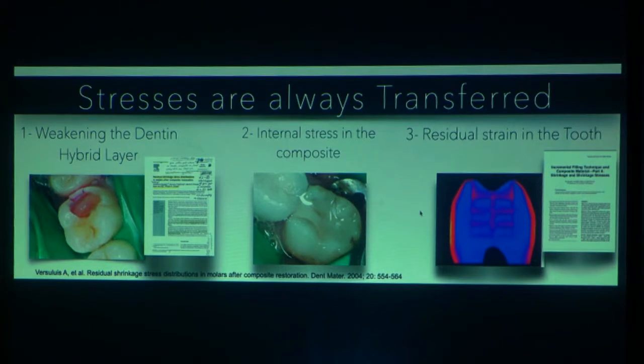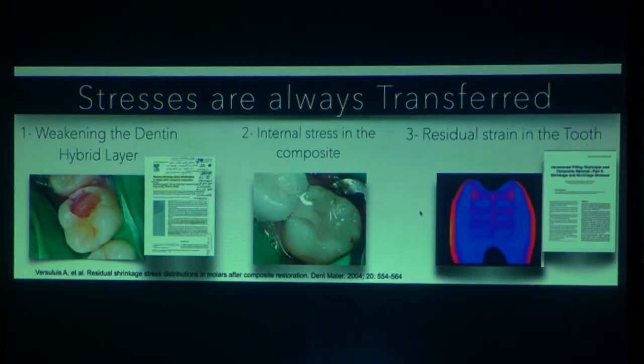3M spent over $1 million, $2 million, with a researcher named John Eick to try to make a non-shrinking composite. They used a composite molecule that actually expanded. It was called a silorane. But the problem is, if a composite expands, then you have stress on the hybrid layer, just like when it contracts. And it turned out that the bonding systems weren't able to be developed. It was a failure. 3M sold a lot of it, of course.